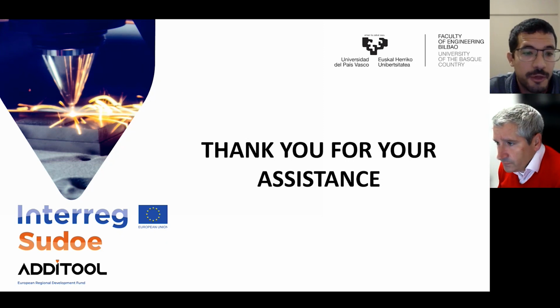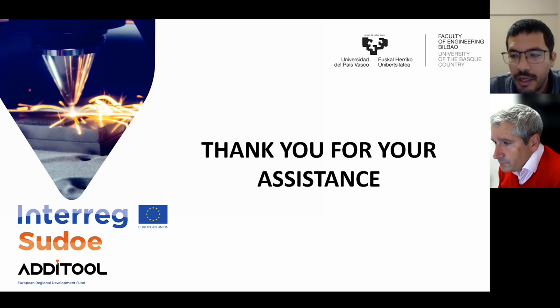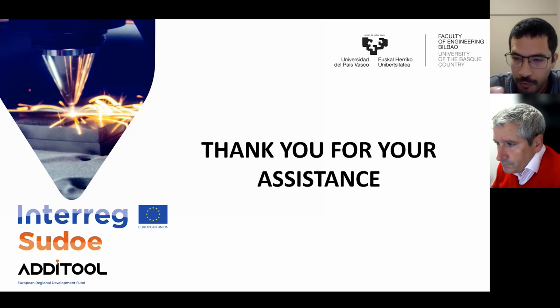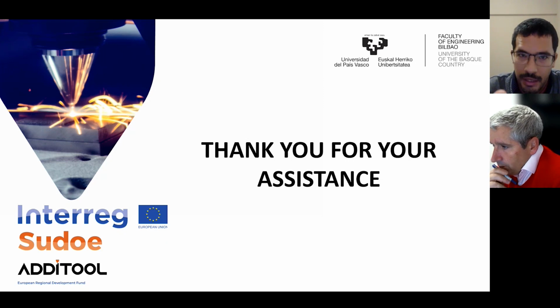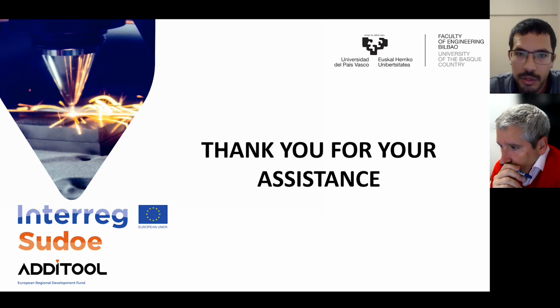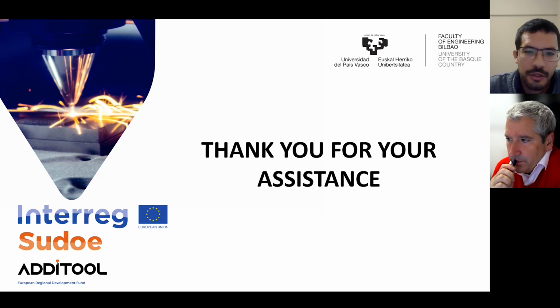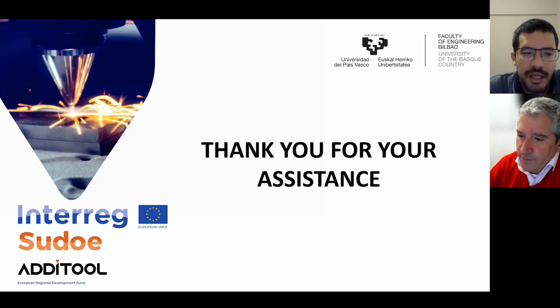In the experimental test that we have performed, we did not realize any stability problems when depositing one material or two materials. And the only thing to take into account is what ADDITOOL has already explained, that the proportion of both materials in the powder feeder and in the deposition plane at the nozzle itself is not the same. So based on the simulation and experimental results, we need to adapt the ratio between both powders in order to obtain the composition that we want in the clad.